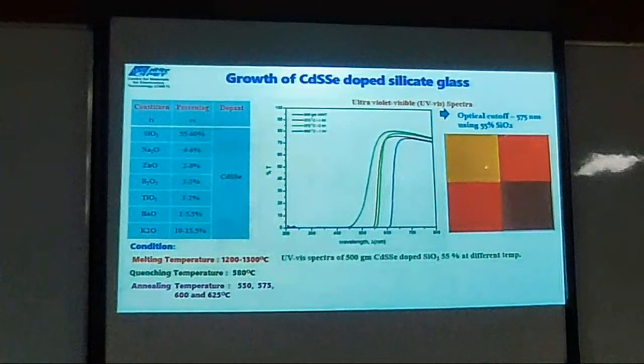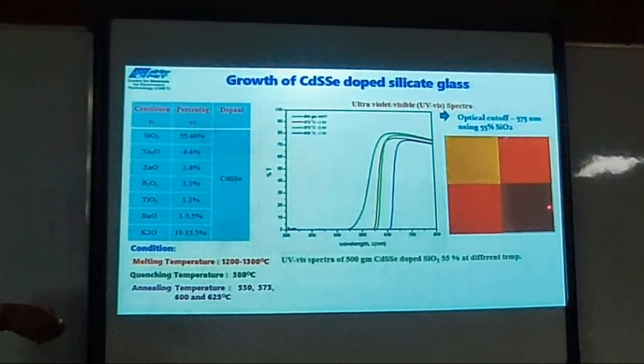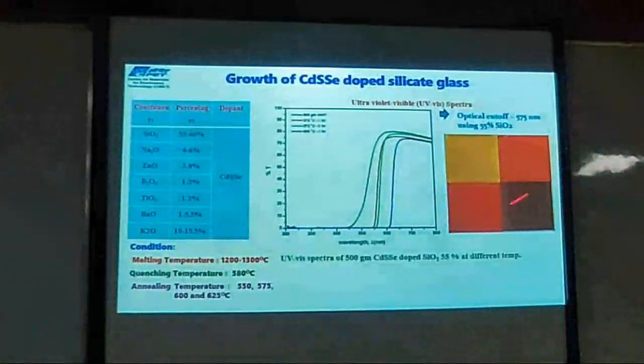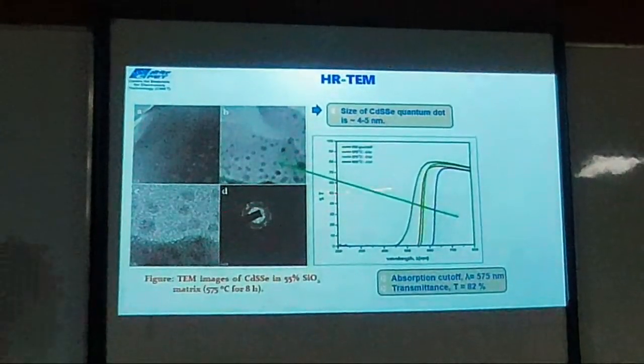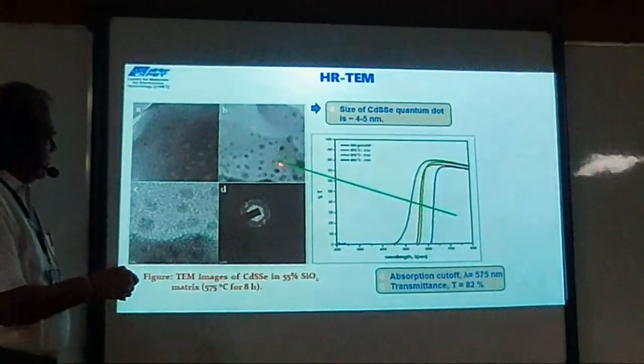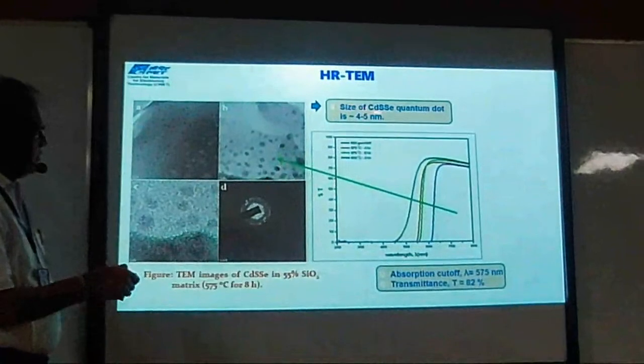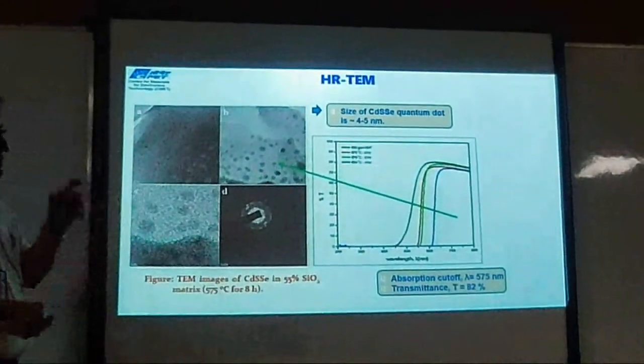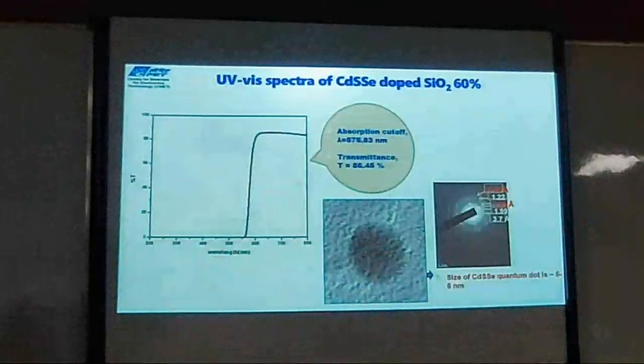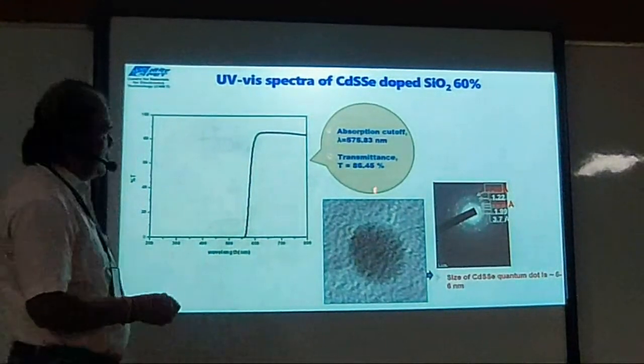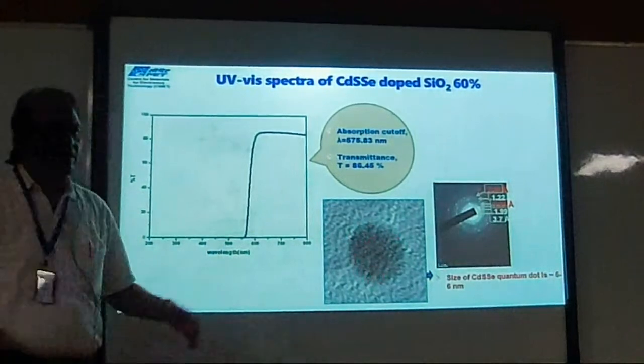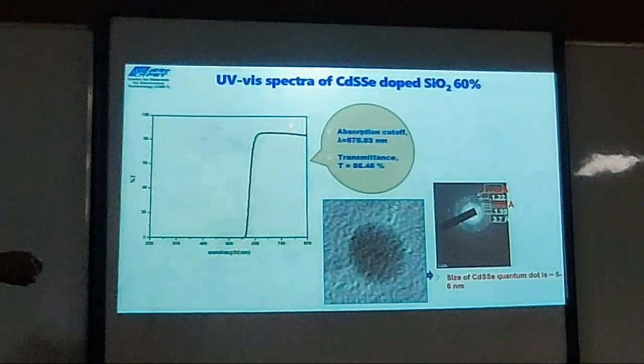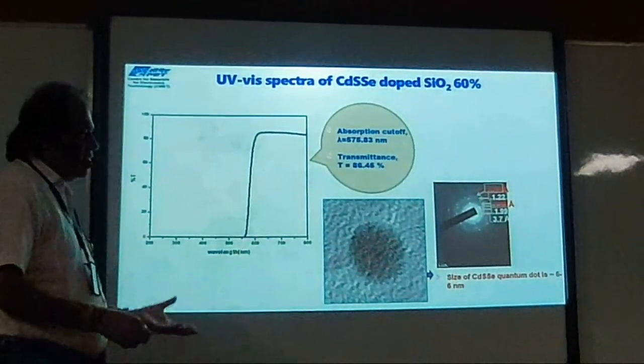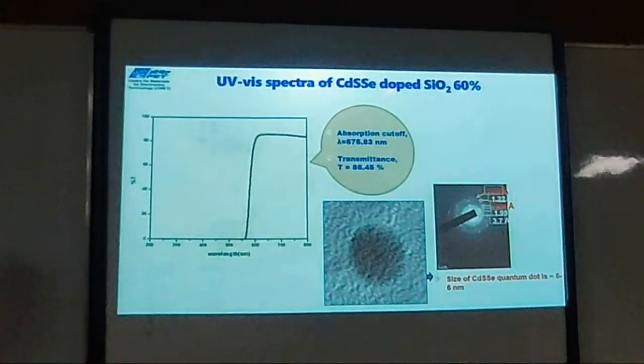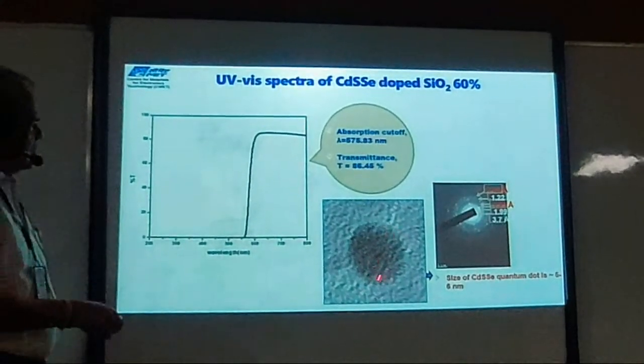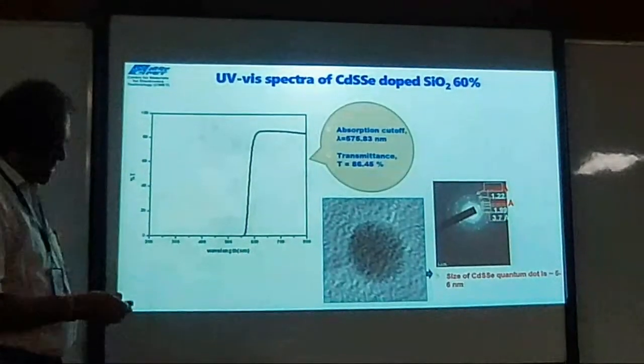Typically, you can see that this may be 2 nanometers, this may be 5 nanometers, 6 nanometers, and 7 nanometers of cadmium sulfide. So with size, we can control the optical properties. And this is a typical cadmium selenide glass, where we have developed quantum dots of 4 to 5 nanometers. It is a narrow distribution, meaning they don't go beyond 5 nanometers. The very steep absorption shows that the size of these quantum dots is very uniform. If the absorption is very broad, then it shows that some are 2 nanometers, some 3 nanometers, some 4 nanometers. But here, 5 nanometer quantum dots are uniformly dispersed in the matrix, where the absorption cutoff is 575 nanometers.